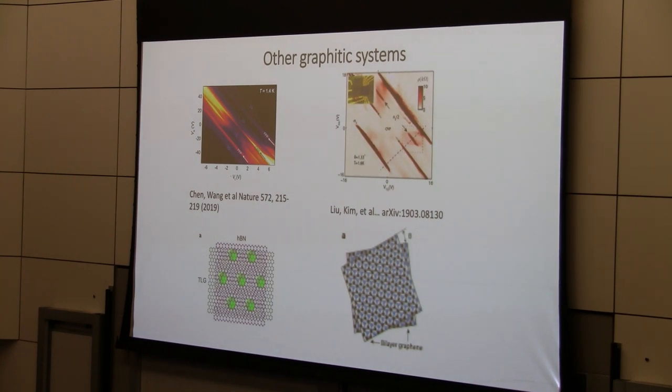Yes. Yeah. Tony, hi. When you compare with the simple theory, how simple is it? Does it take at least vertical relaxations into account? In the very simplest theory, you just have the two sheets that don't move. That's clearly pretty far off. Then you can have local lateral relaxations. So yes, we took that into account in our single particle theory. There's a fairly well-developed literature for how to do that from Koshino and Kaxiras. But even that at the magic angle doesn't quite capture experiment. It's off in reasonably significant ways that are important.